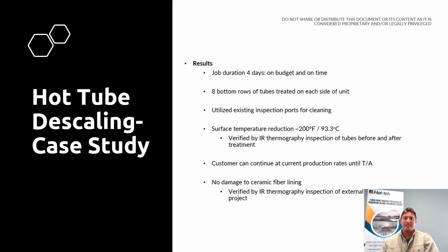So the end of the case study, again, surface temperature reduction, roughly 200 degrees, verified by the IR thermal scans that we just reviewed. This took us roughly 4 days. We did the bottom 8 rows of the tubes by utilizing existing viewports for cleaning, so we didn't even need access creation for those. And again, there was no damage, even though it was a single fired heater, so that there was more of a concern for refractory. No damage was seen by the refractory.